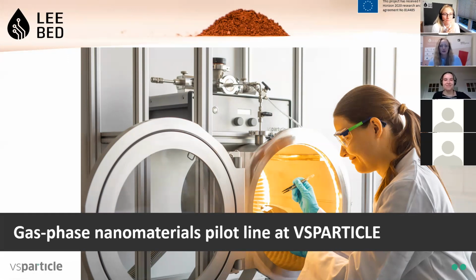Yeah, so it depends on the reactor, of course, but as you saw with the batch reactor, we can do, for example, 10 kilos of copper nanoparticles, while in the flow we can do up to 1 kilo of nanoparticles per hour. It depends a lot on the material that you choose, the precursors you work with. If you have some precursors that have a tendency to get very viscous, there could be different difficulties making them through the flow reactor.